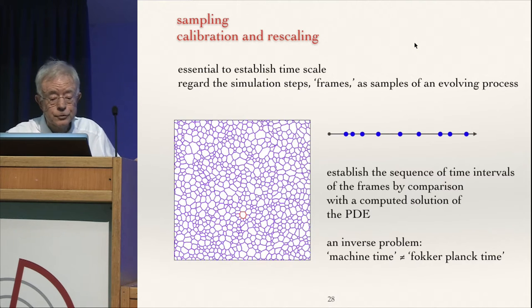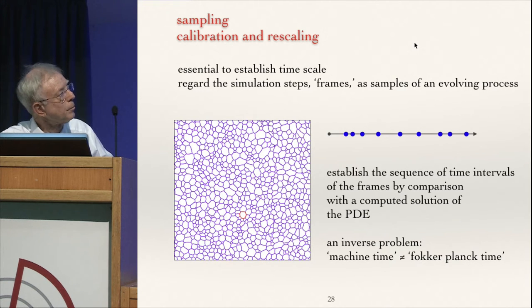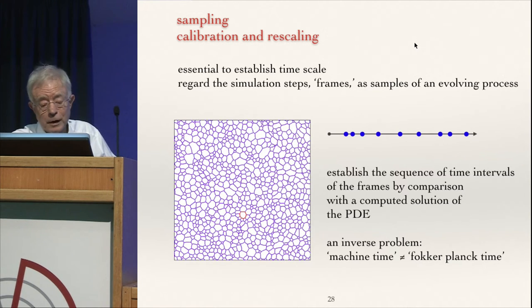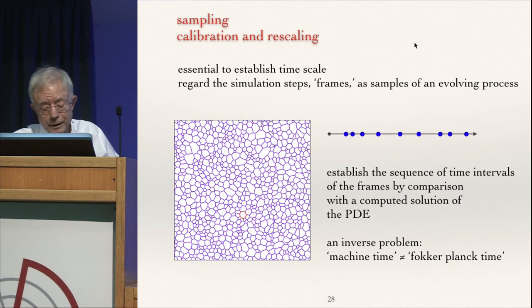So here it's essential to establish a time scale and regard the simulation steps as frames or samples of an evolving process. We have two here. This one, which is our grain growth simulation. I'm not showing you any movies today. And this one, which was the 1D model problem, a lower dimensional model problem, which I'm not going to show you the information for. And so you have to establish a sequence of time intervals of the frames by comparison with a computed solution of the PDE. And then, in fact, we'll check to see whether the solution tracks the PDE. So this is an inverse problem because machine time is not the same as the Fokker-Planck time.